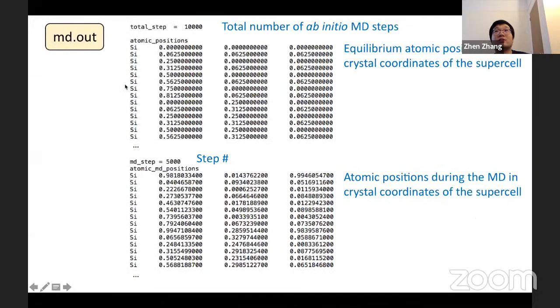Next, let's look at the md.out. So first, the total step is the total number of ab initio MD steps. It's used to claim memory in the code. So you can write down a large number for this. After the atomic positions tag, we put the equilibrium atomic positions of the supercell in the supercell's crystal coordinates. So as you can see, this is the equilibrium positions for the 128 atom supercell of silicon. For each MD step, we first put the step number. Then after the atomic MD positions tag, we put the atomic positions in the supercell's crystal coordinates.